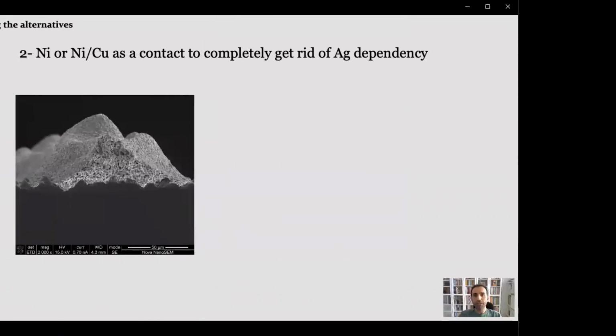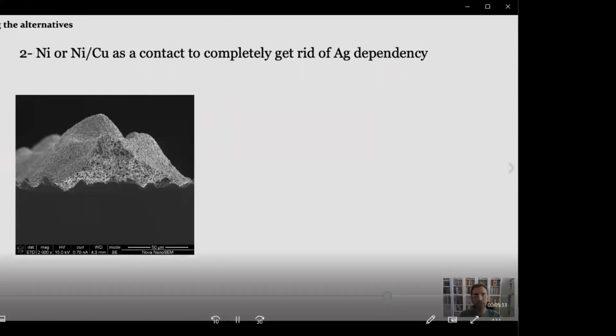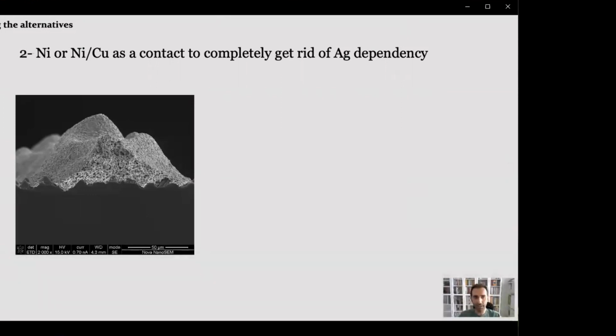So what happens if we try to print nickel as a single layer contact? Printed nickel contact is not very common, but there are some studies, including mine, that show it can serve the purpose if the resistance problem can be overcome. Even though the contact you see here looks great in terms of aspect ratio, the high contact resistance suggests that nickel made a Schottky contact with silicon, and it is reducing the efficiency.